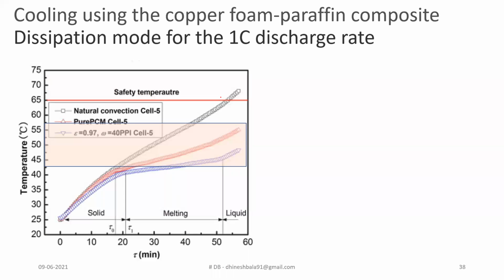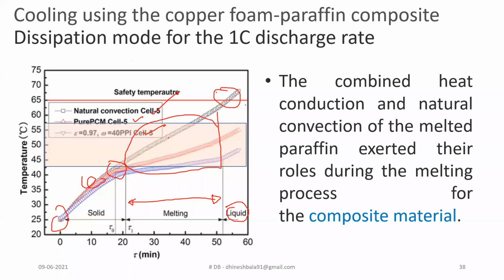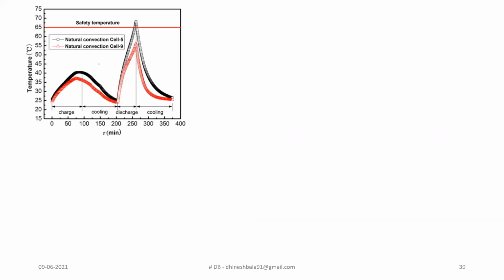And further, the study has been focused on different discharge rates. So from 25 to 42 degrees Celsius for all three, whether it is natural convection, a pure PCM, or a metallic foam, they follow a similar trend. And after that, it starts to melt. So at this melting range only, you can sense there is a drastic change in the temperature profile as compared to the previous two cases. And after that, it would follow a similar trend where it gets converted into liquid. And because of this, you can stay within the safety limit of the lithium-ion battery operating temperature zone. And herewith, I have presented the initial natural convection study.